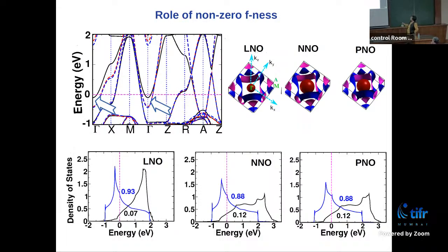So I show you here what exactly is the effect. For praseodymium and neodymium, this axial orbital density of states is shown with the black, and this is basically the nickel x square minus y square density of states, two-band model. So projected to these two orbitals, one is the x square minus y square, and another is the axial orbital. Zero is set at the Fermi level. So you see in case of the neodymium and praseodymium, the occupancy, yes, I will finish very soon. So the occupancy, because you have one electron really, here 88% of it goes to the x square minus y square channel, but 12% goes to the axial orbital channel, both for praseodymium and neodymium. For the lanthanum, this drops to only 7%. So that's a big thing.